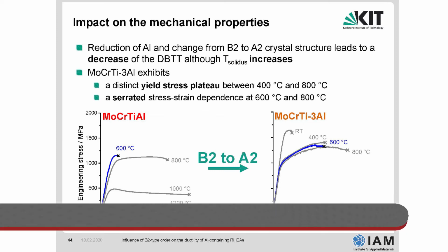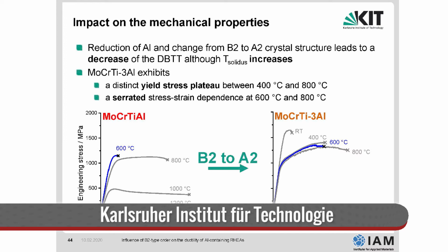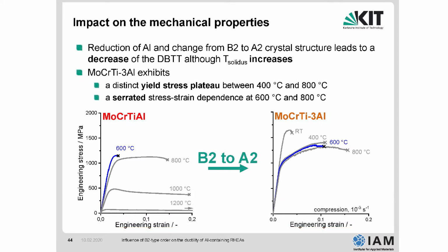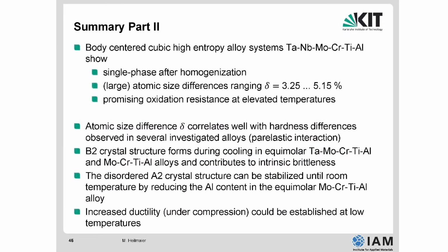So the material is pretty strong. Here see the scale, 1500 megapascal. So it's as strong as a martensitic steel at room temperature, but it is still as strong as a high temperature material at high temperatures. Okay, so the take-home message for these alloys is you have to avoid alien phases on the grain boundaries, and you have to avoid B2 ordering, at least when you talk about the matrix behavior. And this is the summary of my second part.